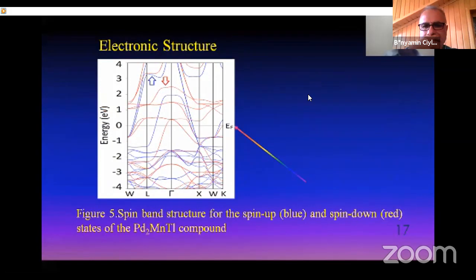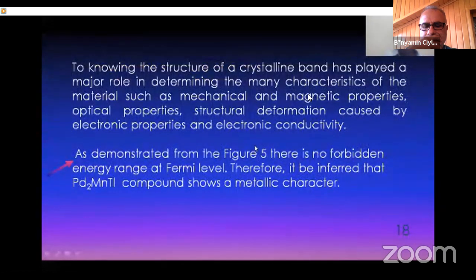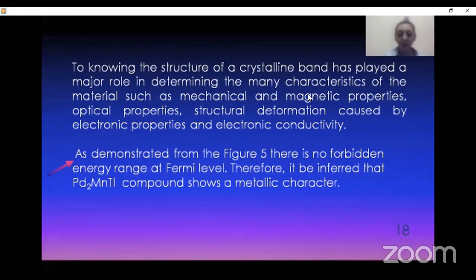Figure 5 shows the spin band structure for the spin up and spin down states of these compounds. To our knowledge, the structure of a crystalline band has played a major role in determining many characteristics of the material, such as mechanical and magnetic properties, optical properties, structural deformation caused by electronic properties, and electronic conductivity. As demonstrated from Figure 5, there is no forbidden energy range at the Fermi level. Therefore, it can be inferred that the palladium two manganese thallium compound shows a metallic character.